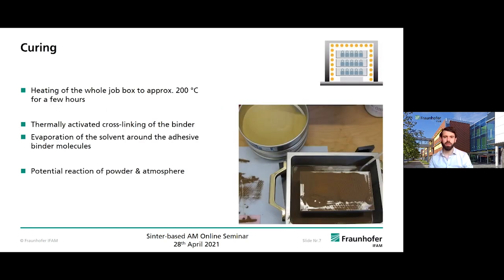After printing comes the curing. In the curing process, it's the first time the material sees some heat, approximately 200 degrees for a few hours, to harden the binder. Whether it is a thermally activated cross-linking process or an evaporation process of the solvent around some sticky adhesive binder molecules. And also in this case, there can be potential reactions of the powder and the atmosphere. On the right-hand side, you can see copper, and there was a real oxidation of the green parts as well as the powder bed. So another atmosphere like argon, for example, could help in this case.